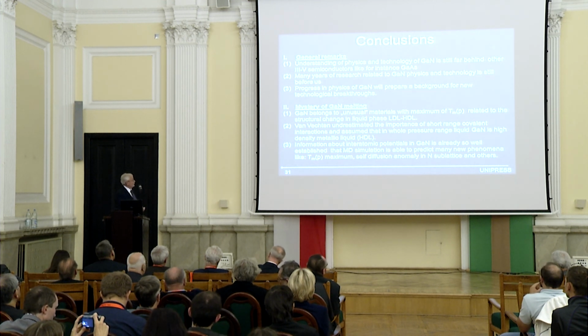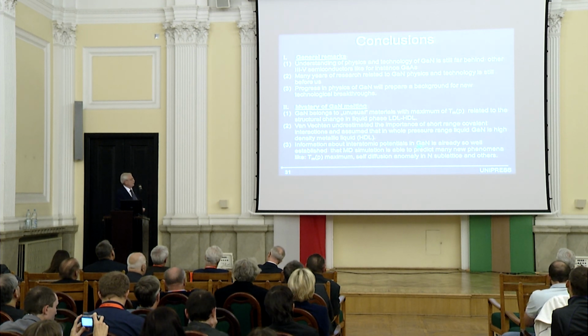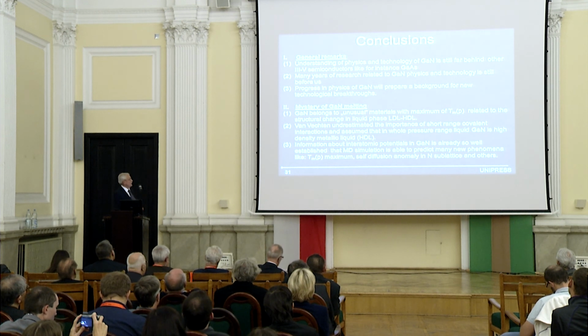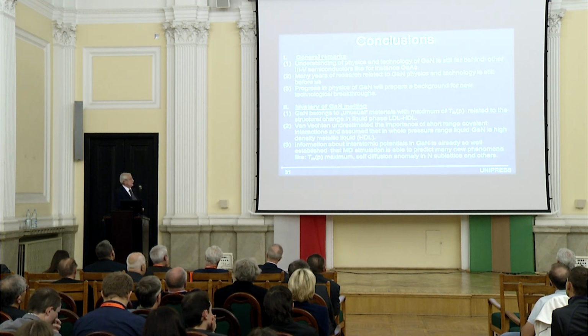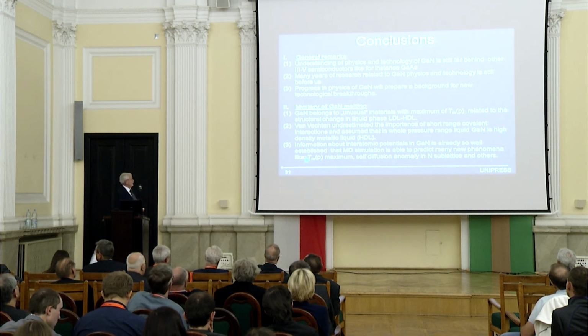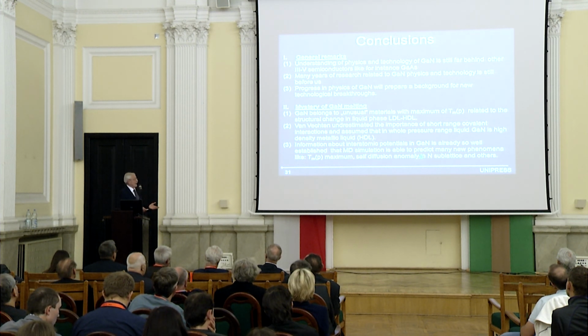And three, information about the interatomic potential in gallium nitride is already so well established that molecular dynamic simulations are able to predict many new phenomena like this maximum or this self-diffusion anomaly, but I'm sure that there are many more effects which can be found by this type of simulations. People, when they see this potential with five parts, are really discouraged and they don't believe that this is a real effect. But I am very convinced that this theory really works and it explains our data perfectly. Thank you.